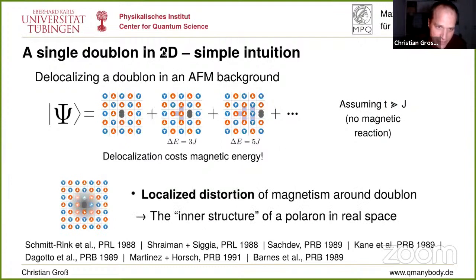But what you get if you assume this is basically that this doublon should scramble the spins in some localized vicinity around its position. Why? Because of the energy growth the further it moves away. So it cannot scramble everything. It should scramble a localized area. And that shows you that what you intuitively would expect is really the picture of a polaron